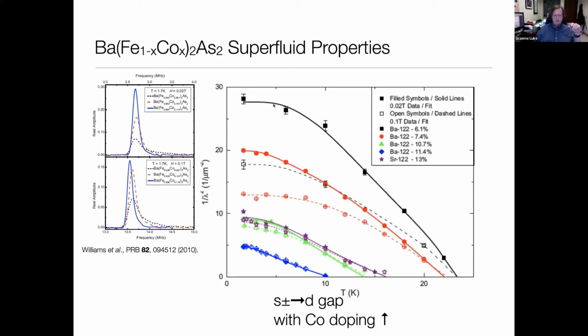You see its temperature dependence changes from being quite flat at low temperature to coming in with much more of a slope. And this is associated with a change in the pairing symmetry with doping in this material.